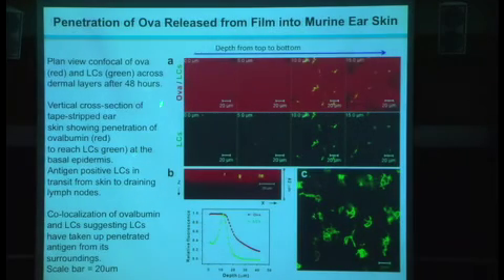And in this work, we found that we're labeling using confocal ova red, and the Langerhans cells are labeled green. And as we go down from the top of the skin into the depth of the skin, ova penetrates very nicely into the mouse ear tissue. We also see that the Langerhans cells dwell at about this 10 to 15 micron and lower level.